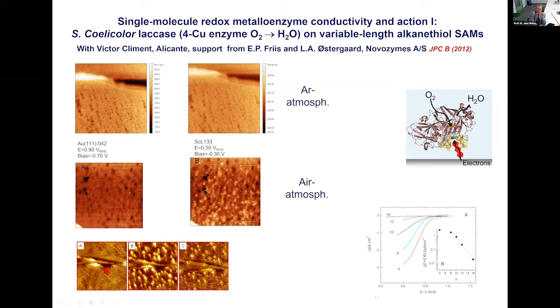And here it is in a different view. Here, no oxygen, then we let oxygen in and all the molecules flare up. And then we try to brush it out again, and obviously we have partly succeeded. This also shows that you have to blow argon in for quite a long time before all the oxygen is out.